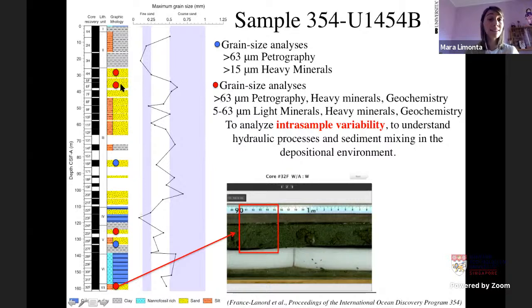And then in the other sample, in red, we want to analyze two different fractions bigger than 63, and we analyze petrography, heavy minerals, and geochemistry. And we want to compare this with the fraction from 5 to 63 microns, where we analyze light minerals, heavy minerals, and geochemistry. Here we can analyze light minerals, and we cannot analyze petrographic composition, so we analyze only the light fraction.